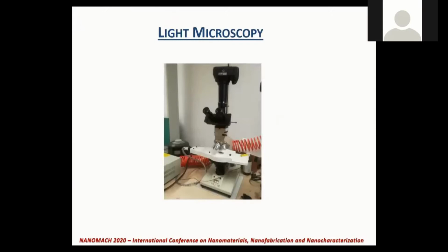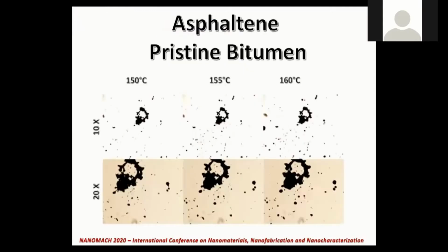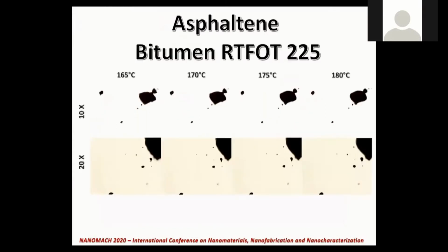Light microscopy. In the next slide, we show the light microscopy analysis of the asphaltenic fraction of the bitumen. The asphaltenes of the unaged bitumen begin to melt around 150 degrees and are completely liquid at 160 degrees. Those of aged bitumen, being oxidized, begin to melt at higher temperatures, in particular around 165 degrees, and are completely liquid at 180 degrees.